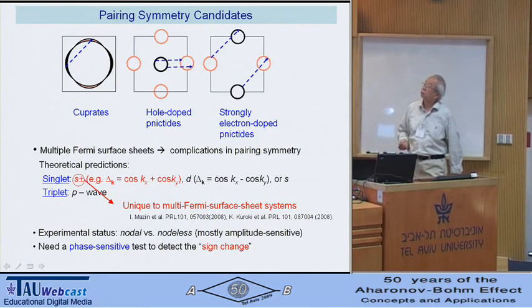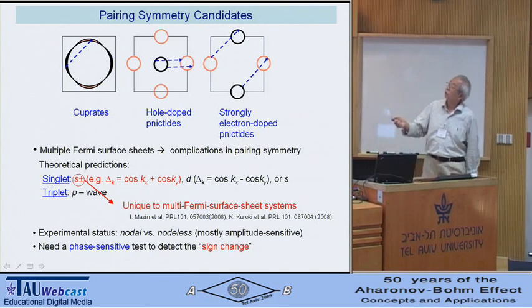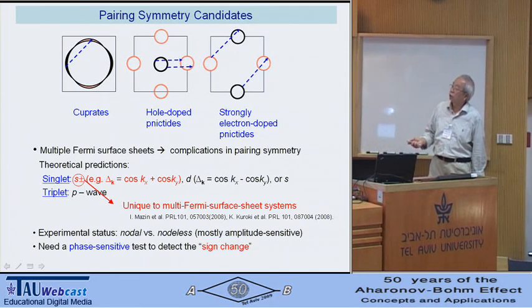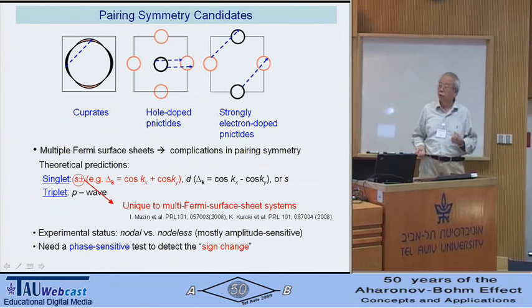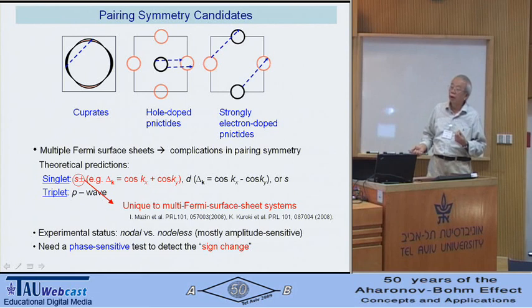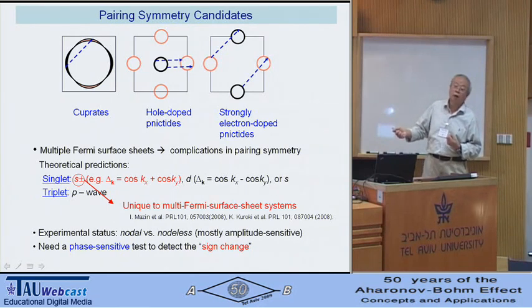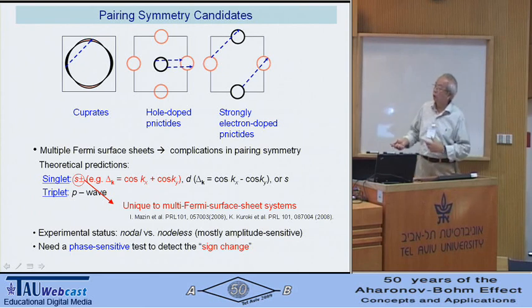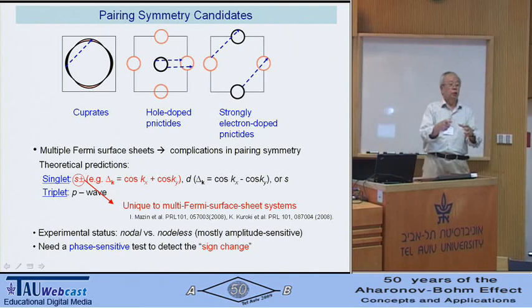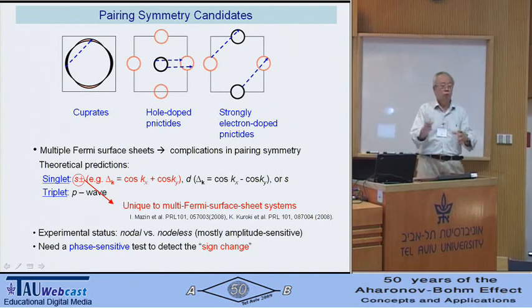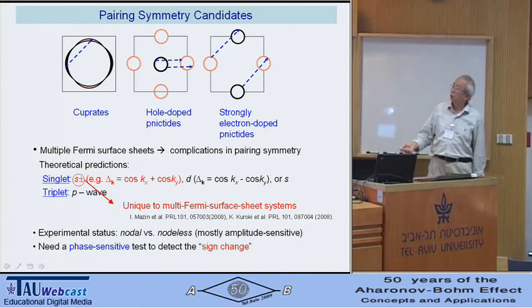And as a result, it's very interesting. The Fermi surface is very complicated. Of course, that leads to complication in determining the pairing symmetry. Now, the theoretical predictions about the pairing symmetry, based on spin fluctuation models, say that it could be S plus minus. In other words, if you have a pair scattering process going like this from one Fermi surface sheet to another, that will give you the so-called S plus minus. Each Fermi surface sheet is S wave, but between those two sheets, it changes sign. So if one's plus, the other one's minus. That's why it's called S plus minus.